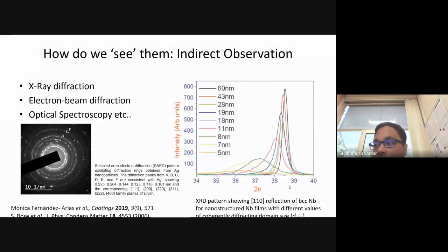As we reduce the number of layers that are available for interference, the quality of the interference fringe goes down, and that gives rise to the broadening of these X-ray reflection or diffraction peaks. Now, there exist algorithms using which we can accurately characterize the size of a crystalline domain in a sample down to about 1 or 2 nanometer accuracy.